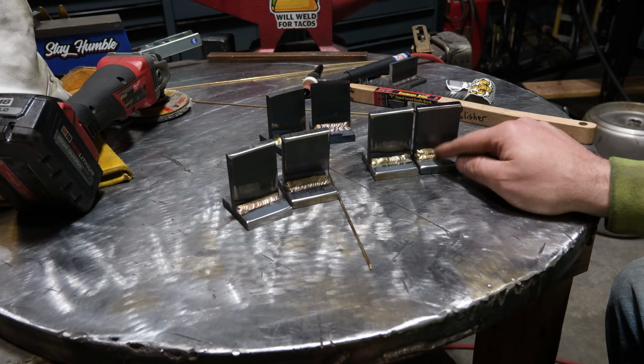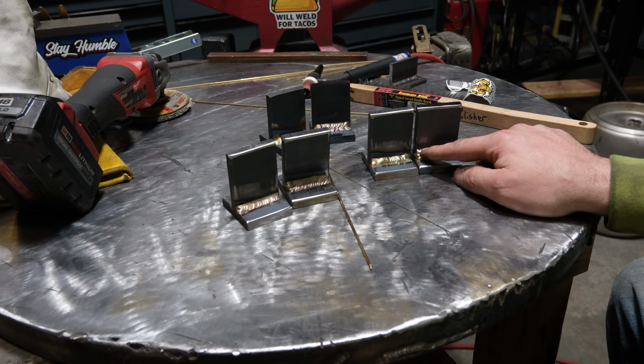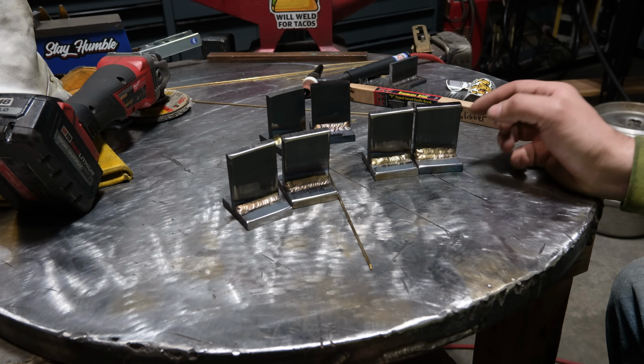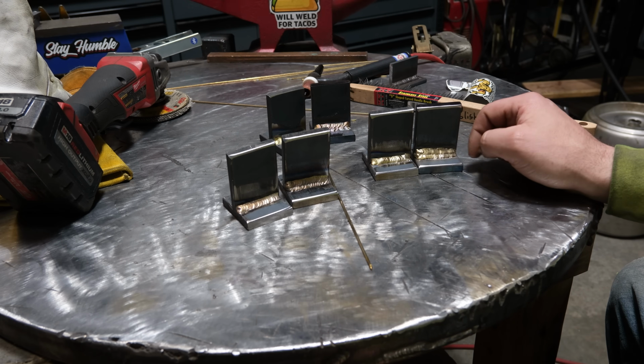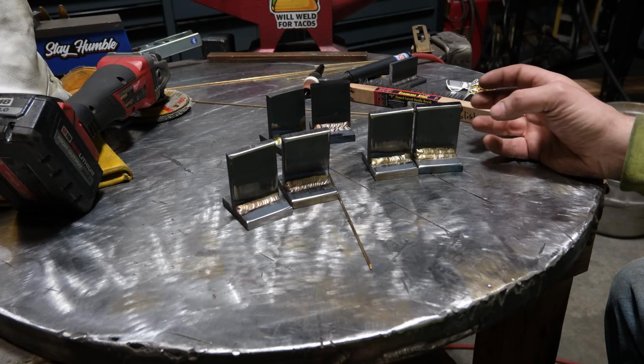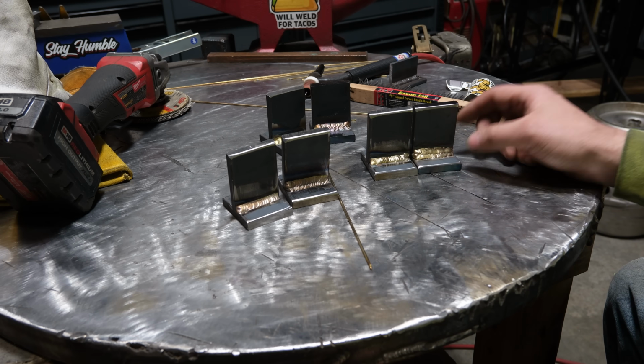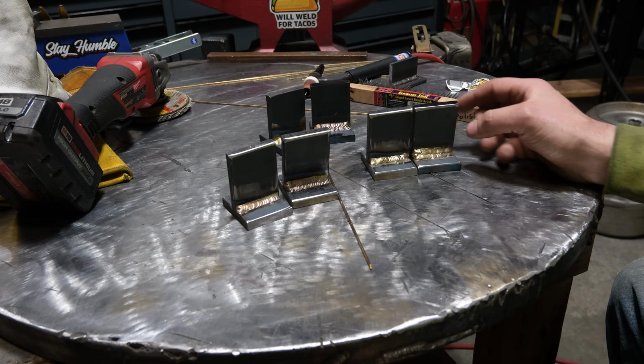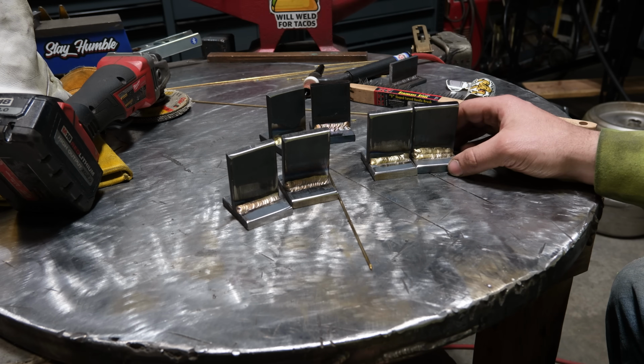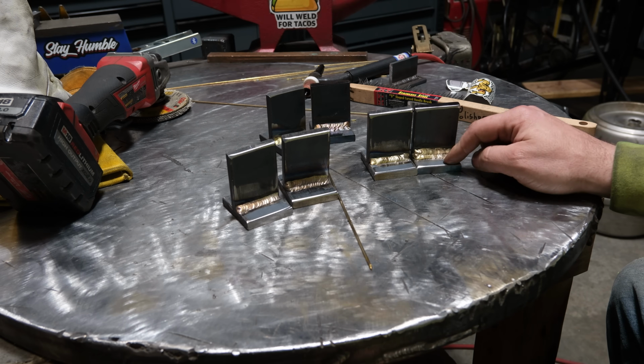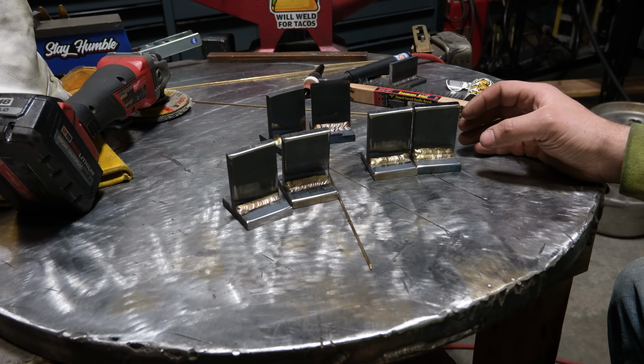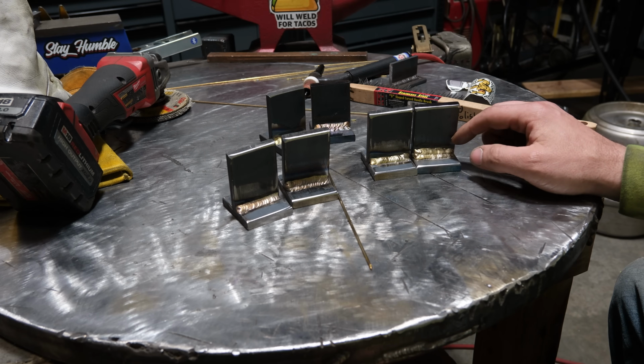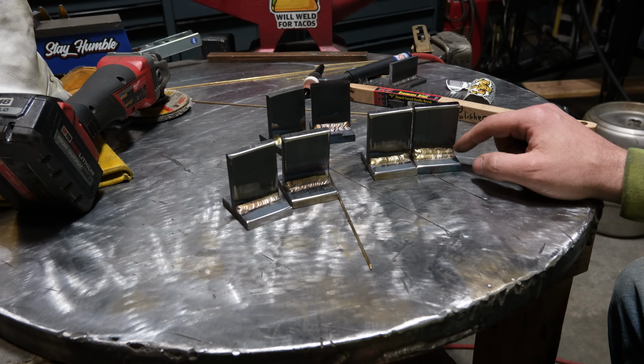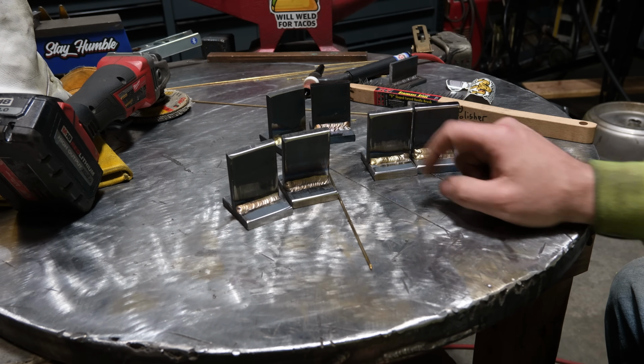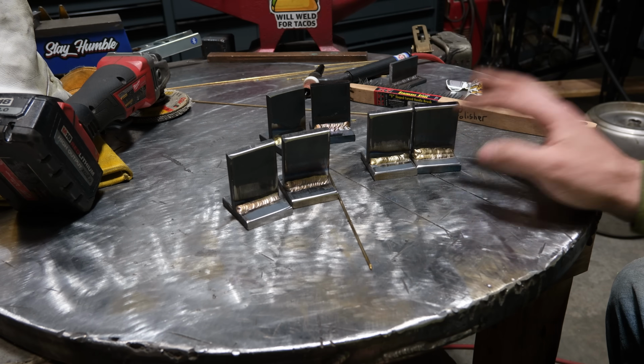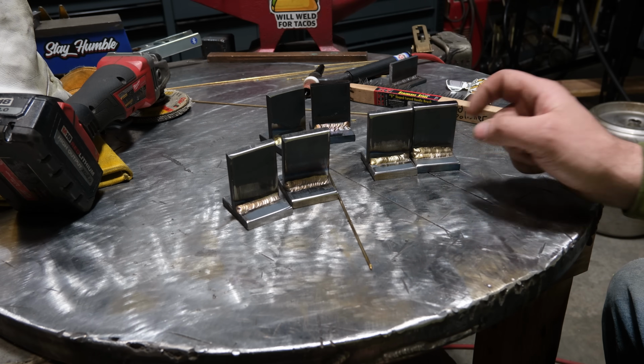Now this, I probably should have done a little bit better of a job cleaning. There's quite a lot of crap that was floating out of this. And you guys have got to remember on AC, which is what I welded this aluminum bronze with, that AC has electrons jumping from the area around where you're brazing to the tungsten, and it has a cleaning action even on normal steel. Now the weird thing is, if you were to try an AC TIG weld on steel, you would probably just contaminate your tungsten pretty quickly, but it does work with aluminum bronze. However, if your stuff isn't perfectly clean, you're going to get a lot of crap floating around in the puddle. Single pass went a little bit better, but for the strength of these, I don't think that's really going to matter, that's a little bit dirty.